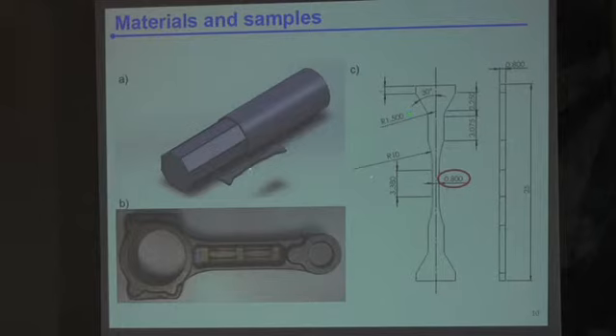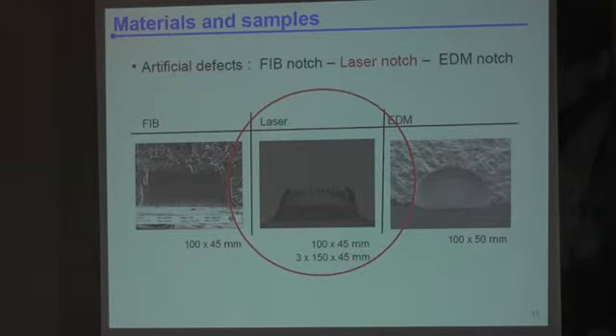As I explained, those samples are either extracted from the surface of the cold extruded bars to different strain levels, or directly from the skin, the forged skin of the component, shot blasted or not. We have worked with cracks initiated from artificial defects. This is a strong assumption, this is a strong thing to do, because your cracks do not naturally initiate from defects, which might be defects resulting from the forging. On the other hand, we tried. We spent nearly one night trying to initiate the cracks from a forging defect, and it's not very effective. So you spend time looking for a crack, 4 days at the synchrotron, you lose your time basically.